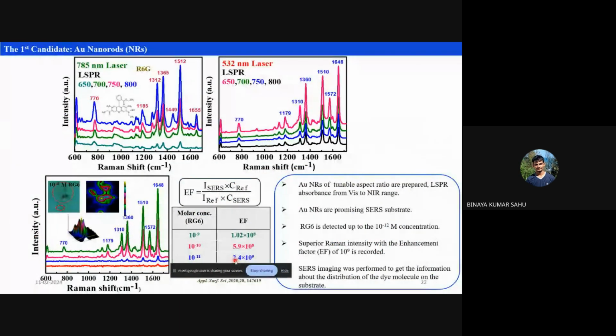And finally, what we are going to use these gold nanorods for is known as surface enhanced Raman spectroscopy. What is that process generally? Using this, you can detect a trace amount of dye or a trace amount of color. Like if there is a very small amount, like here you can see the concentration is 10 to the minus 11 molar. And it's a dye, of course, a test dye.